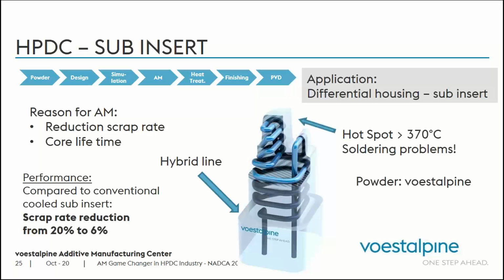And we applied as well the hybrid build approach that I explained before to minimize the cost for the customers, so they increase their profitability as well. And this 370 degrees Celsius soldering problem, by additive manufacturing design, we're able to lower the temperature to 280 degrees Celsius and with no soldering problem at all. So this is a huge, huge improvement.